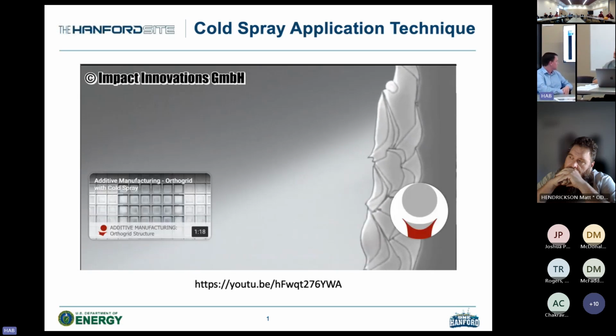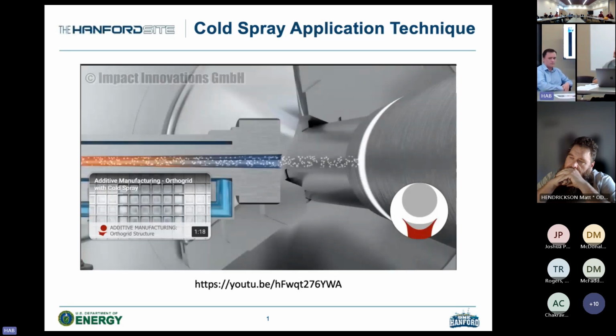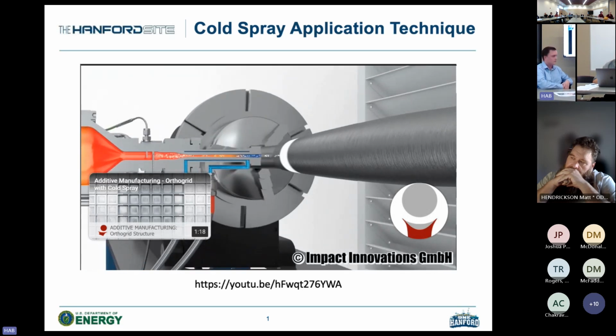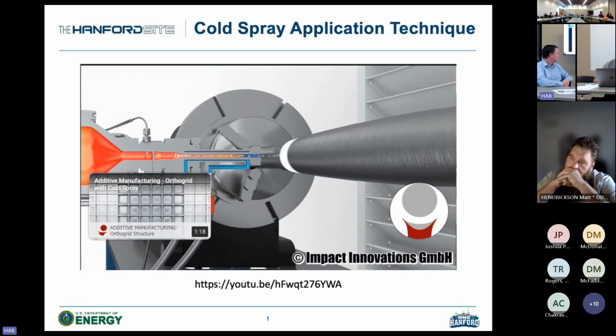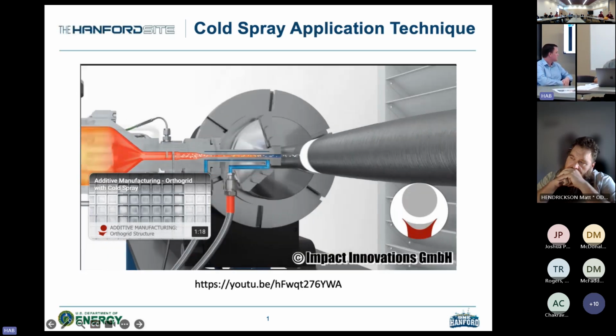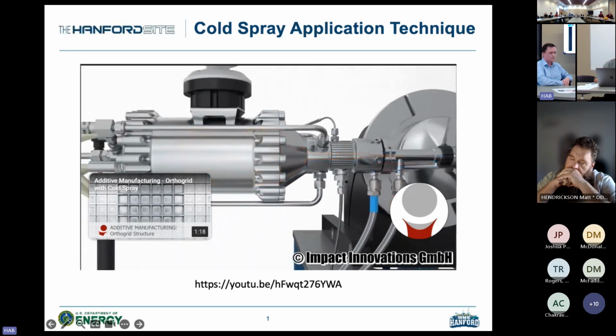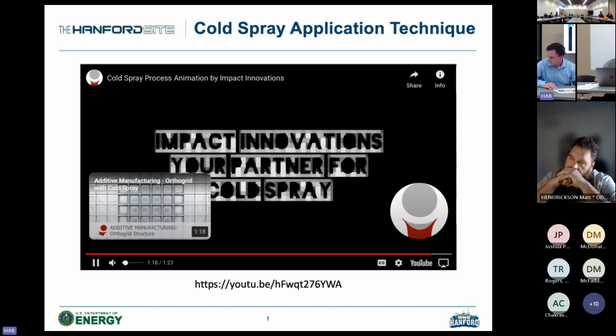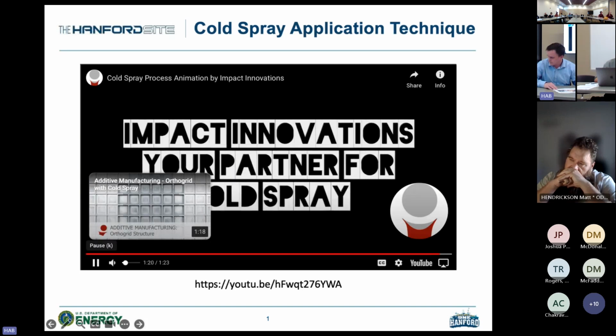This deposition occurs at a temperature well below the melting point of the metal powder, and so it generates no heat affected zone. There is virtually no time for oxidation or for particle phase transformation. So that's the cold spray process. That's about the extent of the fine details of cold spray I'm going to get into.